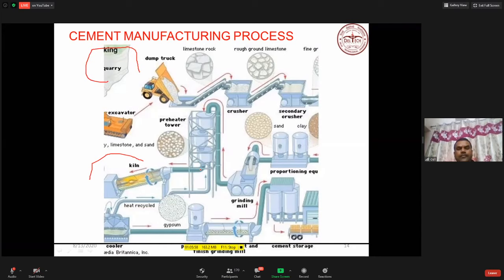So somehow we are using our resources in a way that less heat we have to use. But even though, the production of 1 kg of cement produces 1 kg of carbon dioxide gas. Now you see, when it comes to here, there we decide whether it is OPC or PPC or slag cements. So if it is OPC, then directly this material will come to this silo. From this silo, it will go to the warehouse, where the cement bags will be prepared, and it will be carried to the sites.